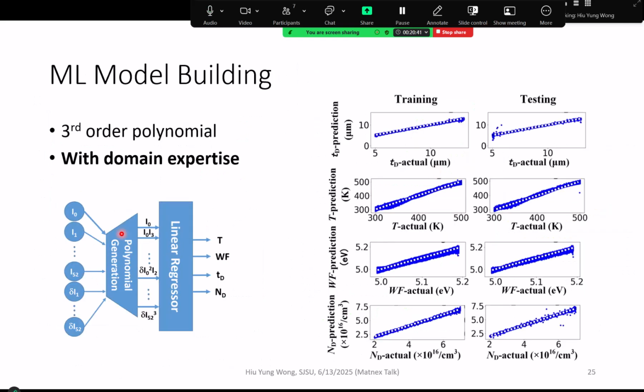So what do we do? We continue the naive way of what we did. We discretize the current, and at the same time we also put in the delta of the current, which represents the slope, right? Because we discretize the interval evenly, the change of the current is just proportional to the slope. So we get the slope also, not just the number. We did some polynomial generation to have different orders and do linear regression to the curves to get these 4 parameters. Okay, so nice, just like what we did before, like a kindergartner, learn everything very well.